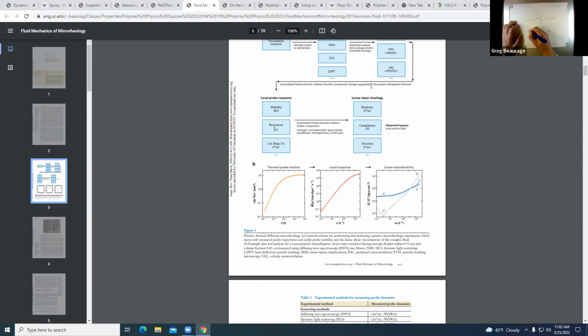In this paper, they use 1% of these polystyrene beads. These are monodisperse beads. He mentions that everyone else has used something like 25%. We're using 1% because they think that 25% perturbs the epoxy reaction. That's probably true. And 1% doesn't, and he demonstrates it doesn't because he runs the cure in the rheometer with and without. That's what I mean by he's covered every possible question on this, except